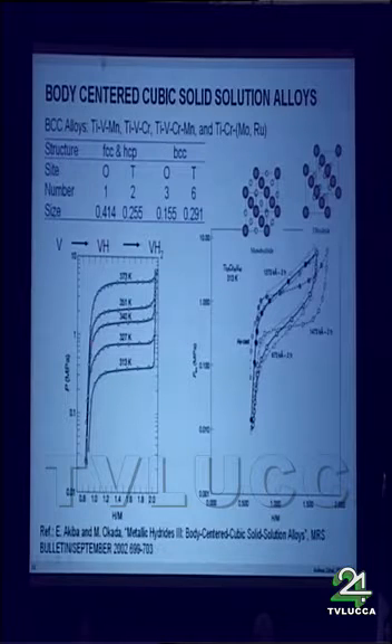Now we have seen how the maximum capacity is defined in metal hydrides, and BCC alloys are especially interesting because the number of interstitial sites in these alloys is, compared to FCC and HCP, much larger. So there are more interstitial sites per metal atom available in these structures. And Etsuo Akiba has studied them since quite a long time, and he also found interesting systems with a high amount of hydrogen in the lattice.